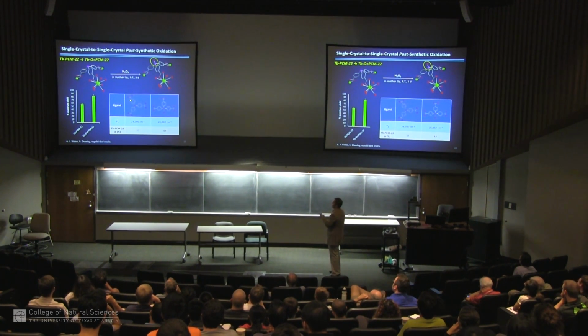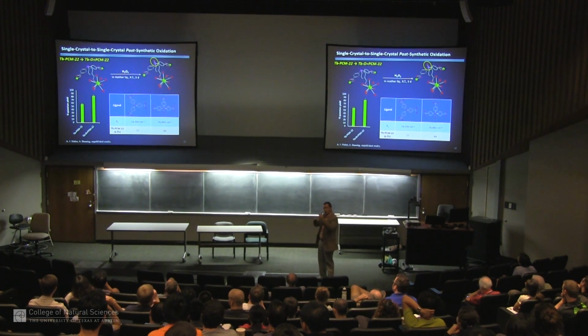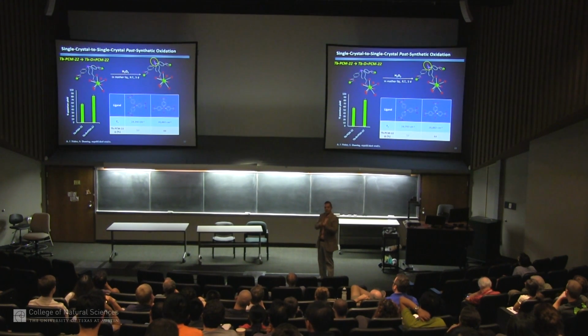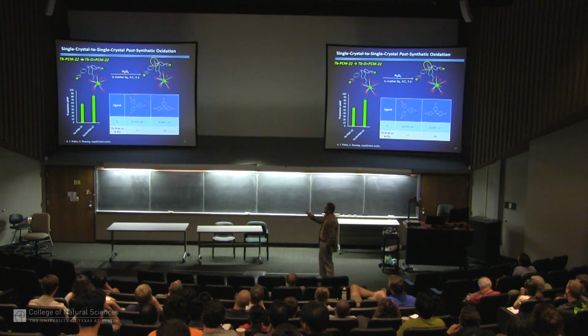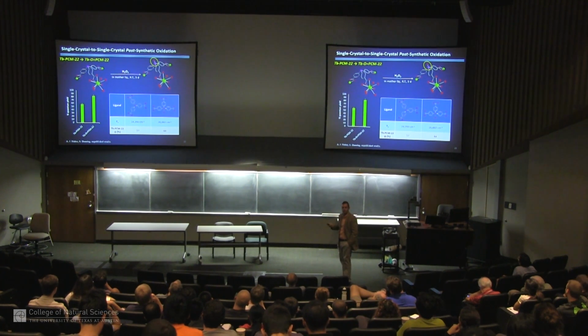Now the reason it's increased the quantum yield is because if you look at the triplet state of the free phosphine or the phosphine oxide, you can see there's quite a difference in the energies of the excited states of the ligands. And so really we're optimizing in the solid state the excited state energy of the ligand to match the lanthanide and get a better energy transfer, a more effective energy transfer. And that's only because we have these phosphines that we can do this. This is a chemically reactive species that allows us to do this. Why do we want to do it post-synthetically? Why don't we just do this before we use the ligand? You can't make the same material. That was the material I showed you previously with the pre-oxidized ligand.